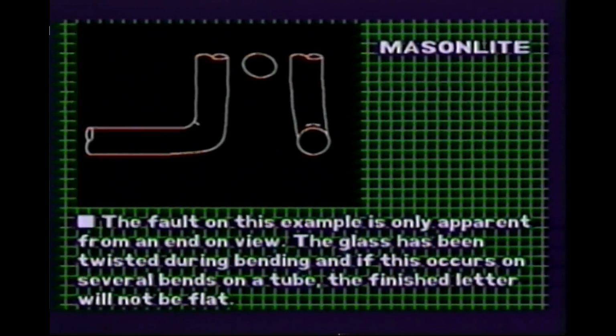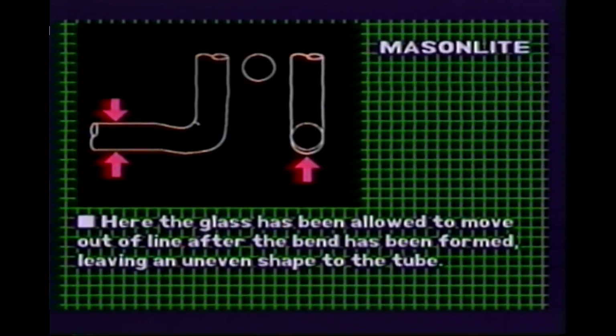The fault on this example is only apparent from an end-on view. The glass has been twisted during bending, and if this occurs on several bends on a tube, the finished letter will not be flat. Here, the glass has been allowed to move out of line after the bend has been formed, leaving an uneven shape to the tube.